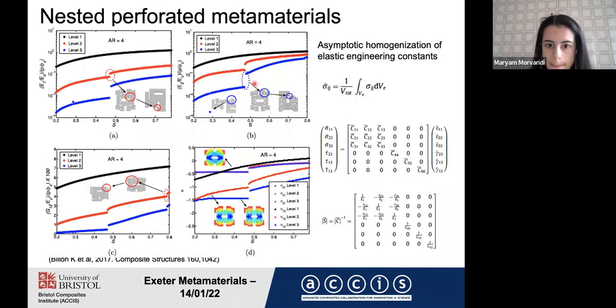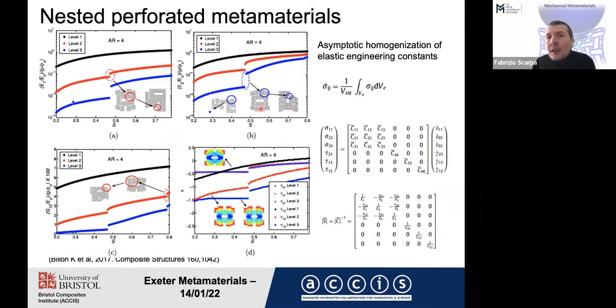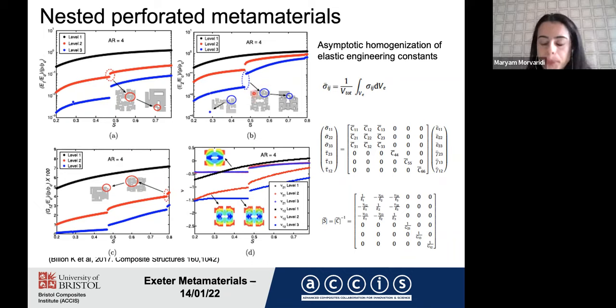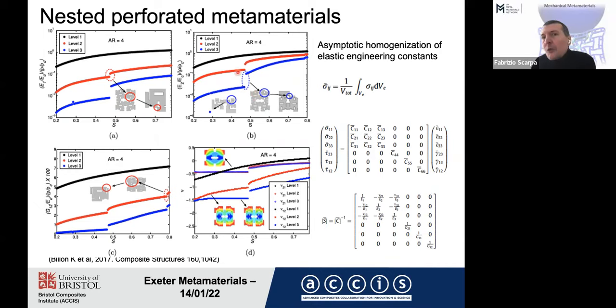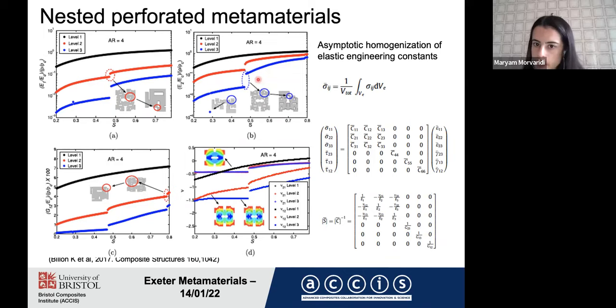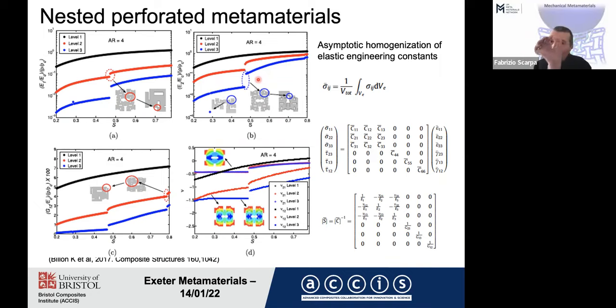Got it. So S is something that we maintain constant at every level of the fractality. The S that we use at level 1 in the main one is the same S that we use inside there. These are ratios. And then you have this kind of discontinuity because in essence we are changing the geometry for S 0.5 in such a way that the small piece that makes the link becomes smaller, and you have a sort of creation of an edge. So it's a question of compatibility of the nested geometries one inside the other.